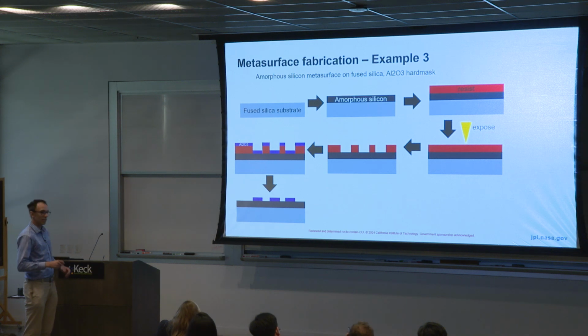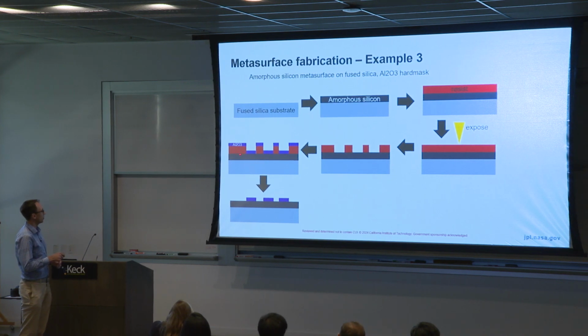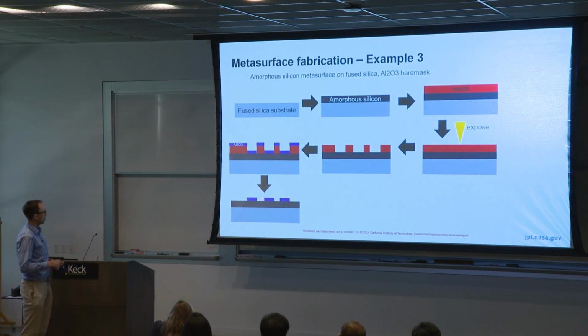the aluminum oxide that sits on top of this photoresist, it now magically floats off into the solvent. If I did a good job at sort of making these vertical or even inversely tapered a little bit. So now I have a hard mask sitting on top of my amorphous silicon, and notice, so here now the tone of the process is slightly different. So where I made openings in my photoresist, I now have my hard mask. So this is now where I'm going to make pillars.